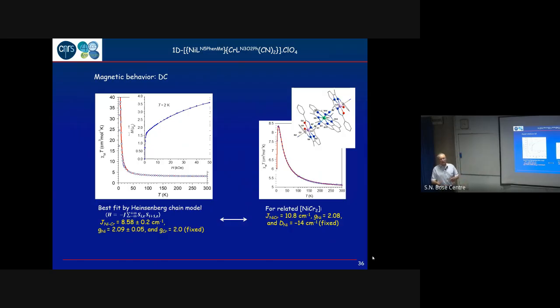And actually, the initial reason why we made the trinuclear species, so this is a trinuclear species made with the same building blocks, is because we wanted to have a precise idea of the exchange interaction, because for such a species, you have an exact model to analyze the data. This is just the behavior of the trinuclear system. So this confirms that it's ferromagnetic. The red curve is just the fitting, and the value we extract is in good agreement with what we get for the chain. What is the ordering temperature here?